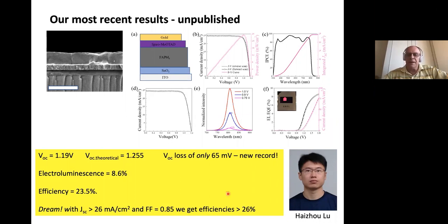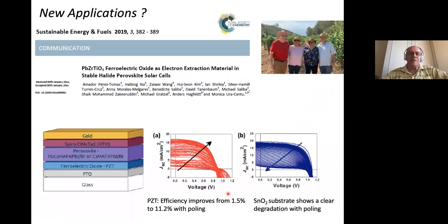I just want to finish also with a surprise coming up with perovskite. This is a work by Mónica and Haibing and others from ICN2, which may lead to new applications. What is tried here is to change the contact to a ferroelectric oxide, which you can pole. So you open up the current in a ferroelectric manner, and then otherwise it's the same perovskite structure. So here is a starting point, low 1%. You pole with applied potential and UV light, and you increase your efficiency up to about 10%, and then it remains fairly stable for hours in that ferroelectric state. So opening up and switching off potential or current with simple poling like that may lead to other applications.